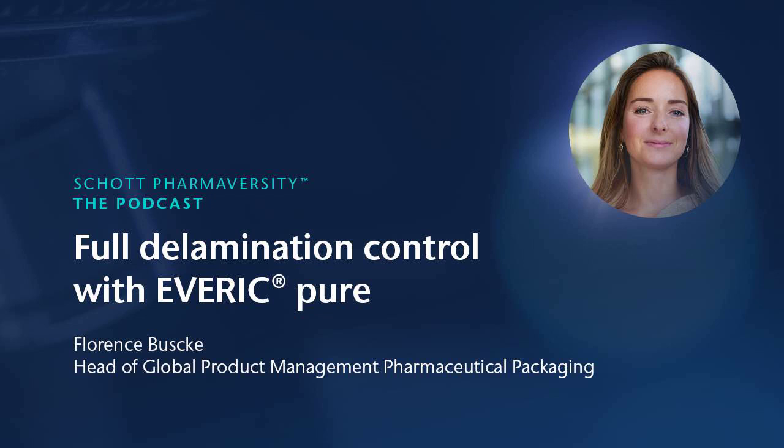So to make it as short as possible, glass delamination is the result of a local corrosion. It takes place in the bottom near area, as we say, of the vial. Those glass flakes appear detached from the upper surface layer of the glass, and it's a local depletion of sodium and boron in the zone between this wall and bottom. And because you ask me more specifically, those thin flakes have a thickness of smaller than 500 nanometers and lateral dimensions up to 1000 micrometers.